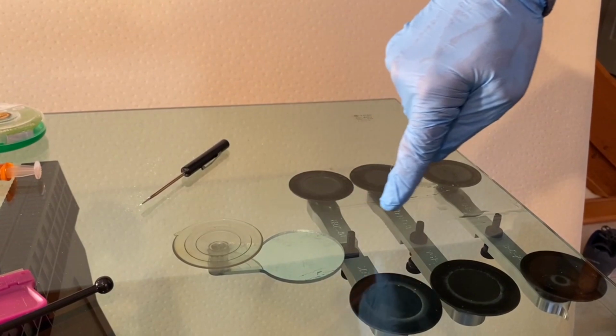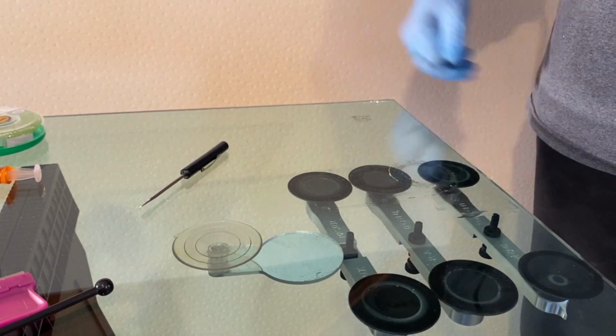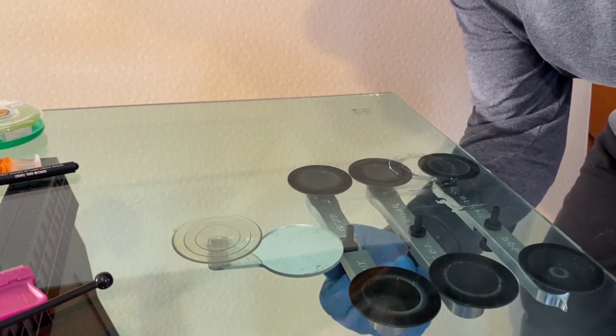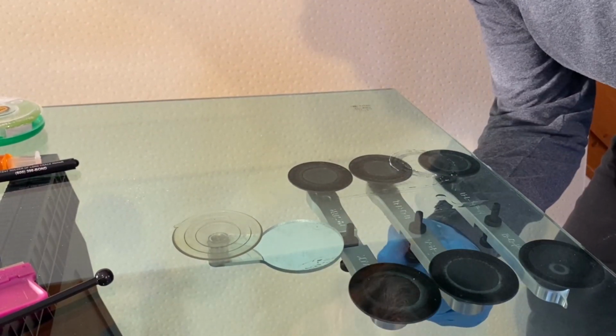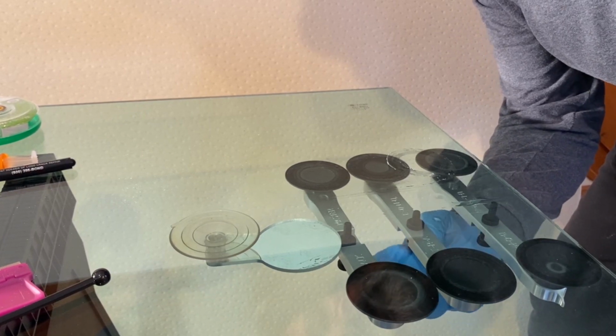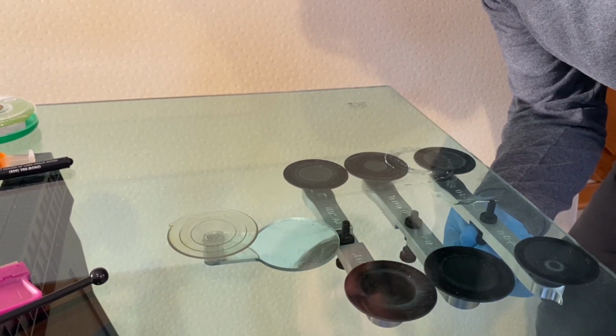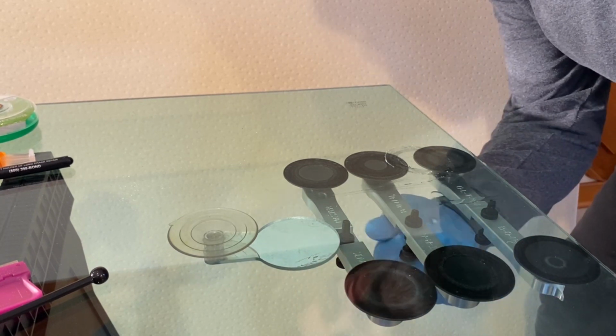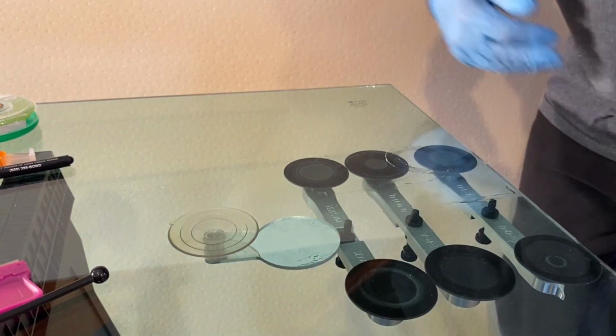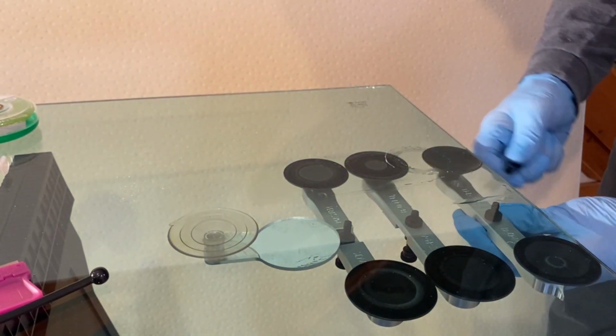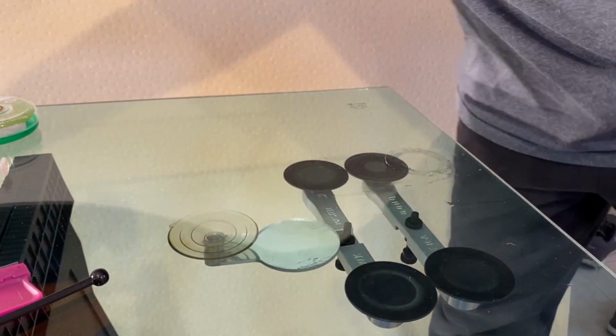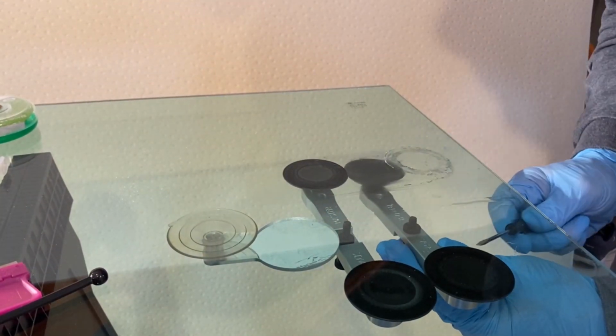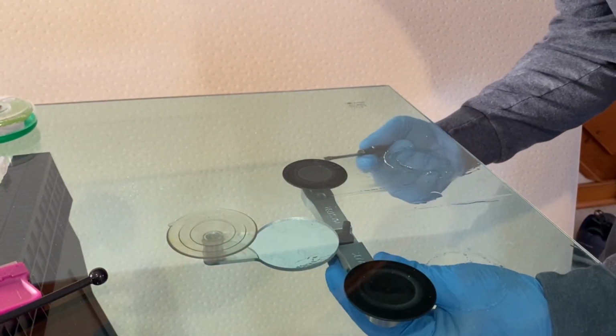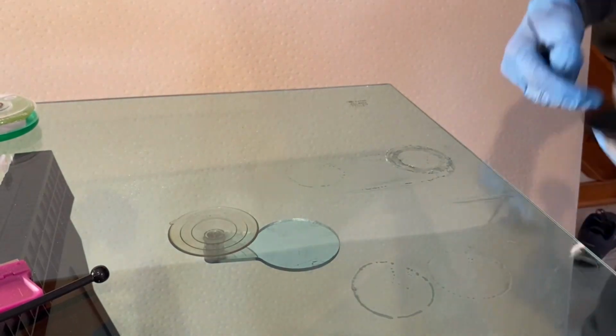Okay, so now you can see this crack is perfectly injected, and it's ready to be tabbed and cured. So always remove the crack opener bolts before you cure. The reason is you want the windshield back into its neutral position. It's a good habit to get into, to not only loosen those bolts, but to take them off. If you left them on there and cured it, when you release the pressure, you will squeeze the resin that's in the crack, and it will refract. It is still bonded, but it will refract, and it won't look good for the customer.